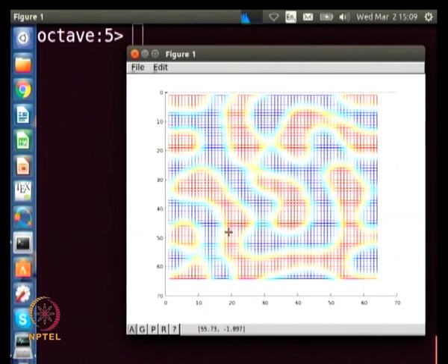So, this is basically spinodal decomposition modeled using the phase field equation, namely the Cahn-Hilliard equation, and implemented using a semi implicit Fourier spectral technique. So, we start with a microstructure which is about 0.5 with some noise, and it evolves to give you A rich and B rich regions, and A rich B rich regions have this typical microstructure, which is what you would see if you did look at a spinodally decomposed microstructure. Okay. So, this is the first part.